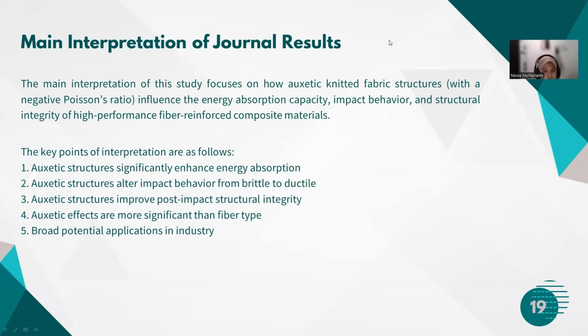Main interpretation of the study. The main interpretation of this study focuses on how auxetic knit fabric structures with a negative Poisson's ratio influence the energy absorption capacity, impact behavior, and structural integrity of high-performance fiber reinforced composite materials. The key points of interpretation are as follows. Auxetic structures significantly enhance energy absorption. The composites reinforced with auxetic fabrics were able to absorb impact energy 2.5 to 4 times higher than composites with conventional jersey structures.